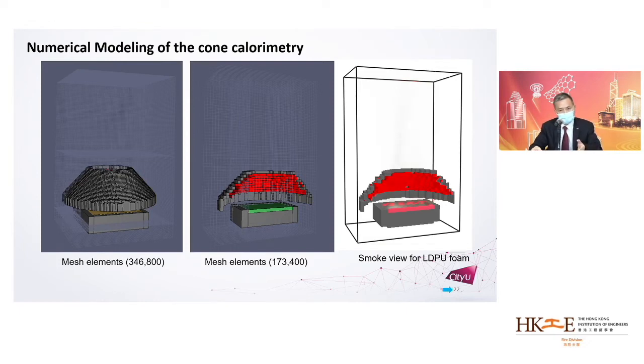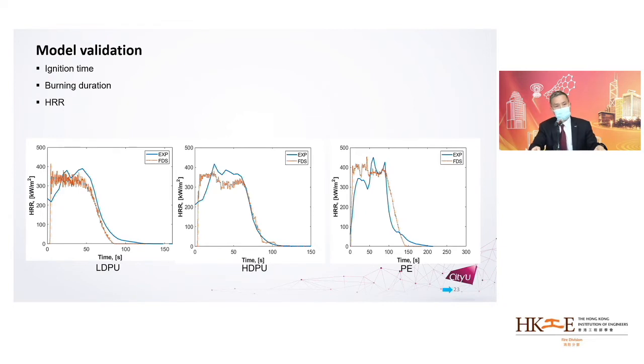we then extend it to a larger scale sample, such as this, in this case, the 10 centimeter times 10 centimeter composite material being experimented and tested under a cone calorimeter. Now, if we take a closer look at the prediction, we can compare the heat release rate of different materials resulting from the experiment as well as the CFD calculation using FDS based on the kinetics we obtained from various experiments. And we can see that it is a very, very good fit in terms of the prediction, which is the dotted line, compared with the blue line, which is from the experiment.